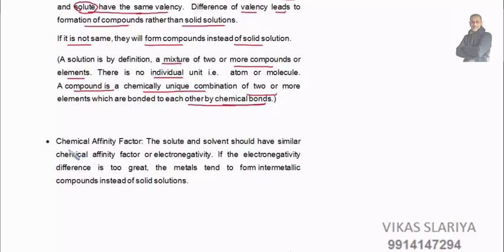Chemical affinity factor. The solute and solvent should have similar chemical affinity or electronegativity. Electronegativity means the tendency to attract the shared pair of electrons towards it. If the electronegativity difference is too great, the metals will tend to form intermetallic compounds instead of solid solutions.